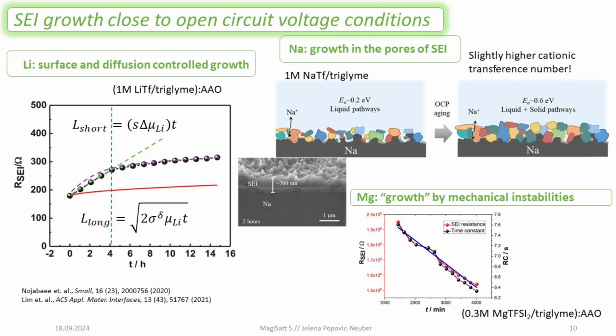On the other hand, with the lithium, we can see that we have a change in different kinds of growth modes. So for the ones that maybe know a little bit more about how the SEI growth modes are typically considered, we typically have this kind of long-term square root t dependence of growth. And this is something that we also see for long-term lithium growth in symmetric lithium cells. But in some specific cases, this is a diffusion-controlled growth, but we sometimes see even this linear surface-controlled growth in the case of lithium. This is not something that you see for every electrolyte under every circumstance, but in principle here we can see it in short term from 0.4 to 4 hours.